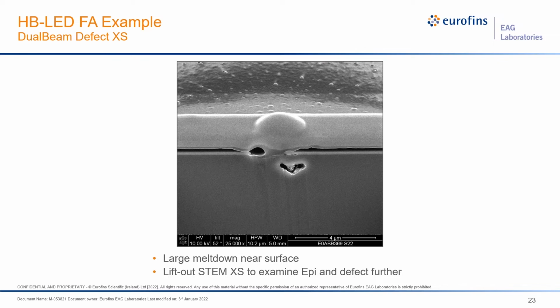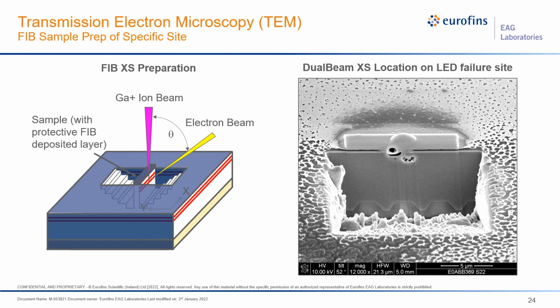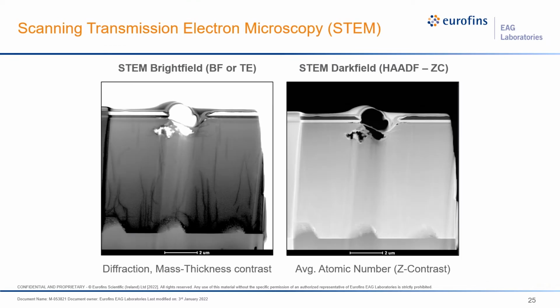In this case, though, it'd be very helpful to get more information about the crystallography within the sample, which we can't get from SEM. So we need to further proceed to TEM and try to examine the epi a bit further. What we can do is use the FIB again to remove material from the backside of this cross section back here. We can physically remove that, undercut it, and then lift this out in situ using a nanomanipulator in the dual beam itself, put it on a TEM grid, and then put it into the STEM.